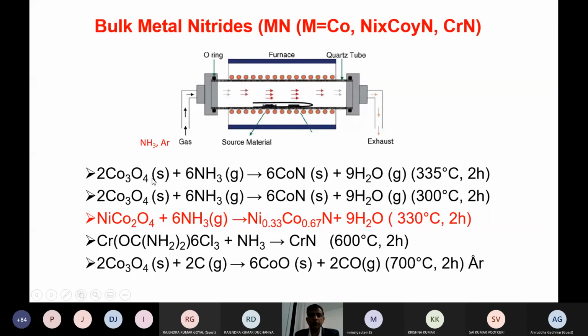So remember the beauty of this method is we can prepare on a large scale. Here the materials should be very porous. Sometimes your materials are not dense. For example, if you take commercial Co3O4 and pass ammonia gas, it will not get prepared. So make sure that the ammonia has to penetrate into the sample. The material should be porous, whatever way you try, that is the logic behind the porous sample. So the ammonia has to penetrate and react to form cobalt nitride.